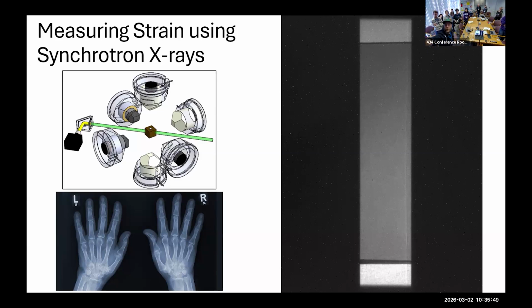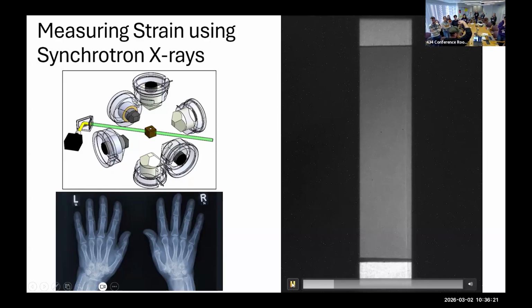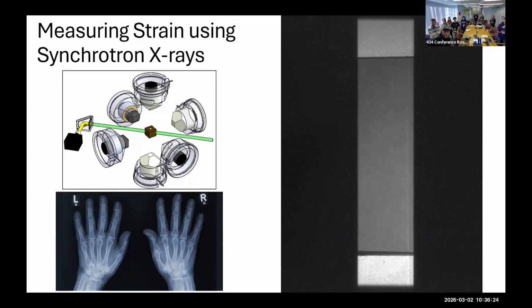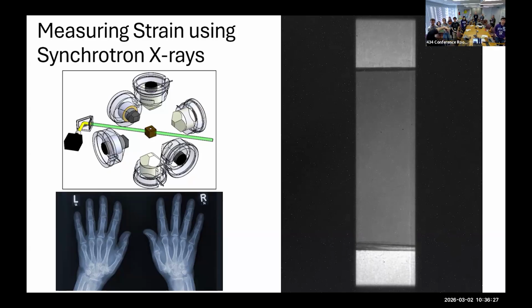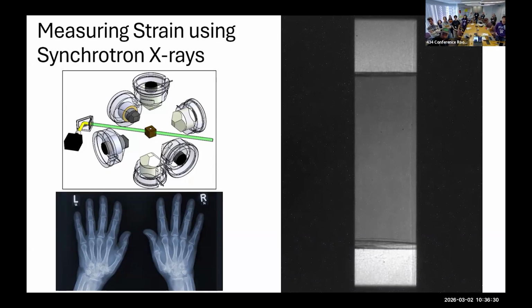So on the ends here, we put some gold or platinum foil or something really absorbent so that we can see an edge to the length of our sample. And then this is a movie. So we're just collecting radiographs, just like you'd get an X-ray. Different materials are going to absorb stuff differently. So the sample will have a different absorption than the pistons. And then we have these really absorbent material on the edges. And then we're just going to measure how long the sample is as we're pushing on it. So you see it's getting shorter because we're pushing on it from the top and the bottom while it's under high pressure. I think too, you can't really see here, but the sample cracked, which we were trying to do.